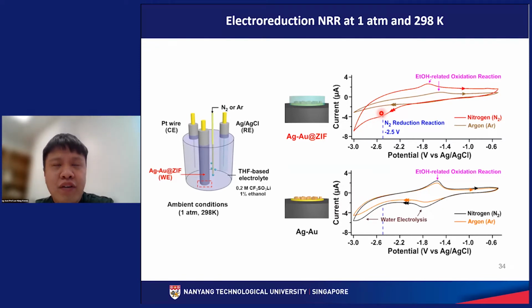Okay, so if we were to compare these two cyclic voltammograms, we can see that this peak over here is very obvious, and it only occurs when nitrogen is bubbled into the system. So in another way, we infer that this reduction peak could be due to nitrogen reduction reaction. Okay, so in contrast, in the absence of any MOF coating, we see that the cyclic voltammograms are similar whether we bubble nitrogen or argon inside the system.